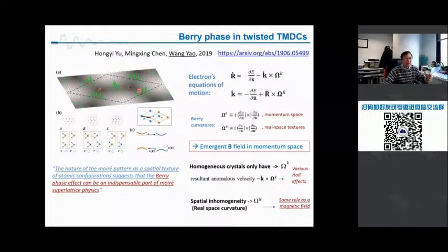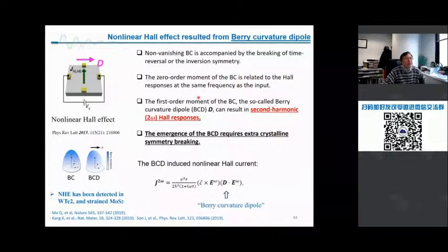Some years ago, people already published that if you highly bend the materials, using a probe on a monolayer, graphene and others, that causes a very strong magnetic field related to the strain gradient. It could be very high, 100 Tesla and so on. So the principle is this: we can make a nice device and then try to measure the Hall effect. We inject current here, but then measure the voltage across here, using different frequency. Theoretically, this is a Berry curvature. If you introduce extra strains, as I demonstrated there, the sample is always inhomogeneous, but then that causes the Berry curvature dipoles.